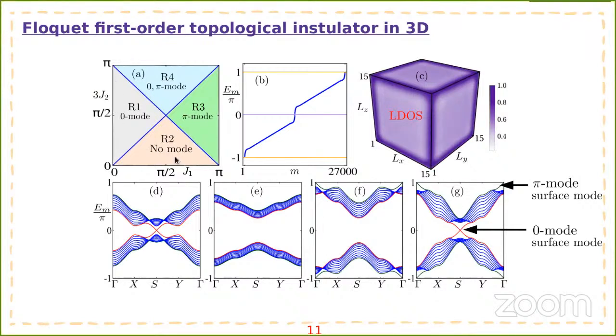Now in 3D, the scenario is also the same. The phase diagram is almost the same, but here it is 3J2 instead of 2J2, and in the phase R4 we can get the 0 energy surface modes, surface modes crossing 0, and also a surface mode near pi, and the density of states is populated around the surface of the system.